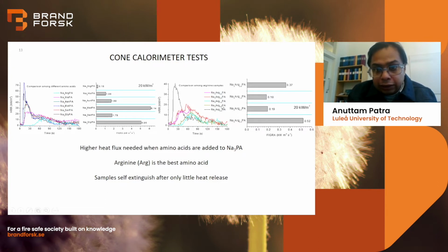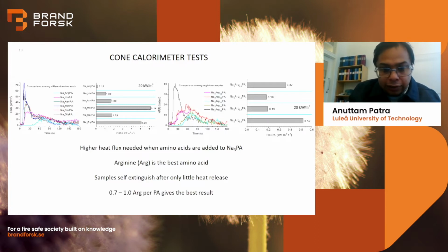But when we increase to 0.7 to 1, then wow, it's really low. So that is the best range in the FIGRA index. But when we are increasing arginine more, we can see the HRR is coming a bit fast. At the peak of the maximum, it comes a bit early and the peak is increasing. So in those cases, the FIGRA index increases again. So 0.7 to 1 range, we have the best flame retardant behavior with arginine.